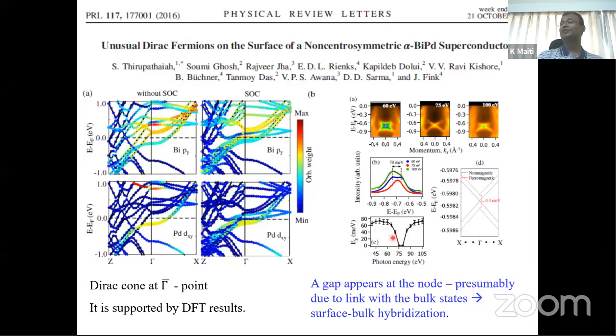Now if there is a gap, it means these Dirac states are not purely two-dimensional surface states, but there might be some link to the bulk. That gives rise to this. But they cannot explain why this doesn't show periodicity. If this is a bulk-like state, then when you change the photon energy, you actually vary kz, so it should show periodicity as a function of kz, which they did not find. They found only zero gap at 75 eV, and on both sides the gap decreases. So this is one unknown problem that was there.